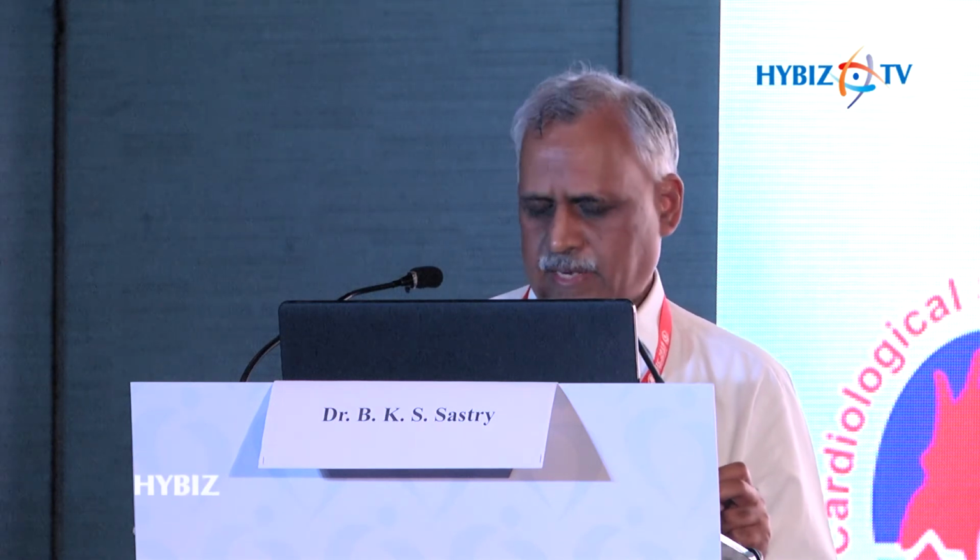Then the partially bioresorbable stents, where the polymer is resorbed over a period of time. You can see this in the Synergy stent. The drug and polymer both get eluted over 90 to 120 days. So at the end of 3 months, neither the polymer nor the drug is there, by which time the neointimal endothelialization should take place. The 1 year event rates compared between the Promus Element and Synergy show no significant difference. In the Synergy EVOLVE trial, the late thrombosis is also not different, but the consideration is that the bioresorbable stents will have better late stent thrombosis rates.